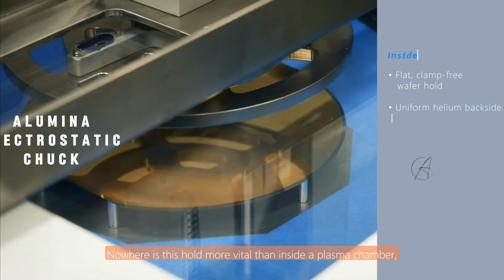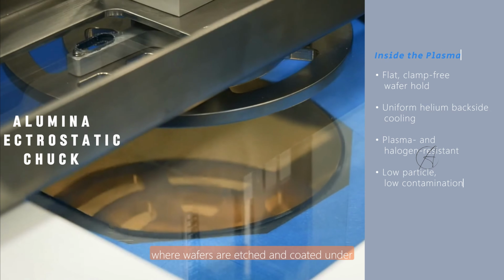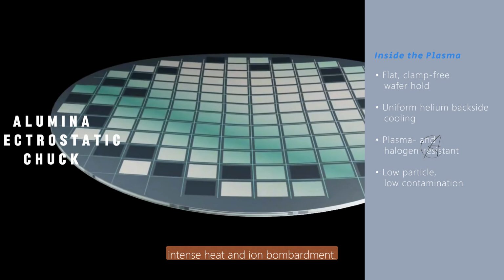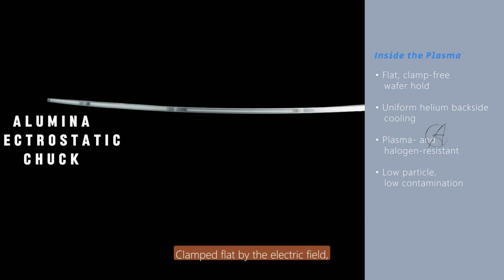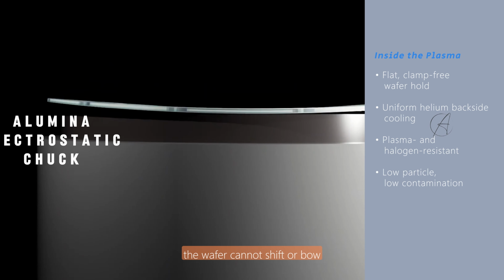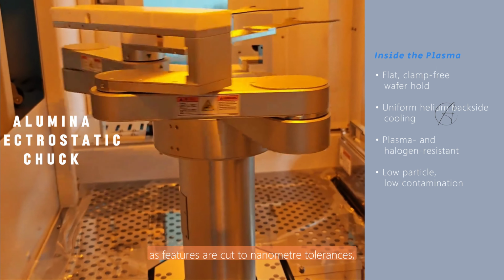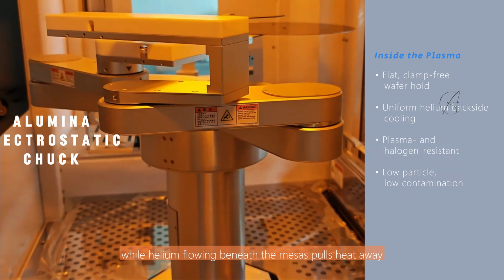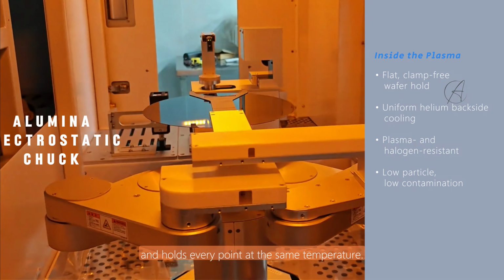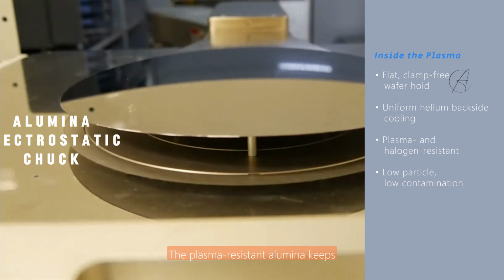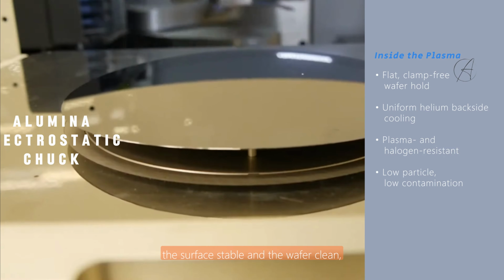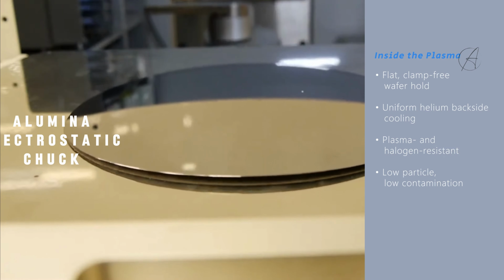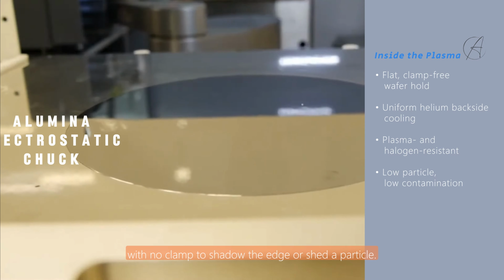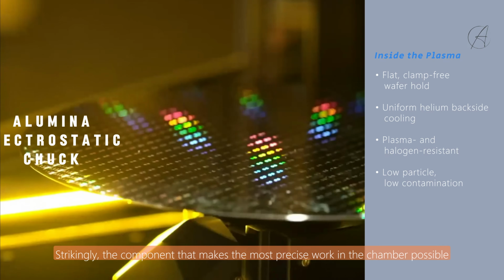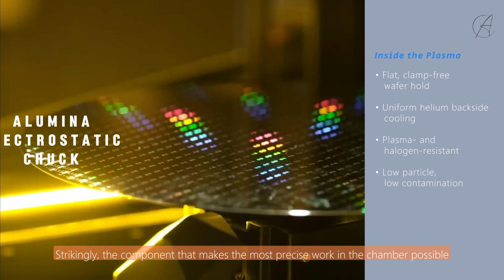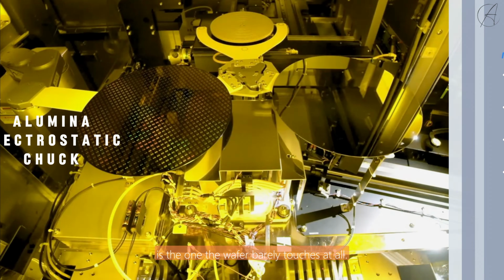Nowhere is this hold more vital than inside a plasma chamber, where wafers are etched and coated under intense heat and ion bombardment. Clamped flat by the electric field, the wafer cannot shift or bow as features are cut to nanometer tolerances, while helium flowing beneath the mesas pulls heat away and holds every point at the same temperature. The plasma-resistant alumina keeps the surface stable and the wafer clean, cycle after cycle, with no clamp to shadow the edge or shed a particle. Strikingly, the component that makes the most precise work in the chamber possible is the one the wafer barely touches at all.